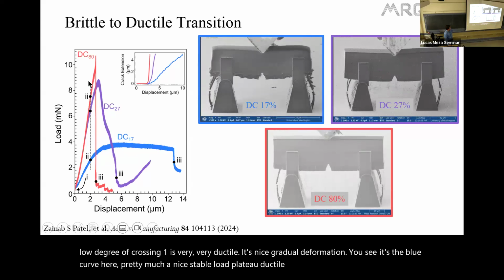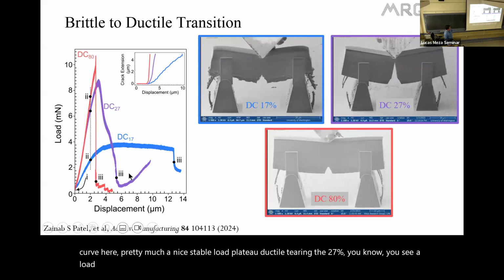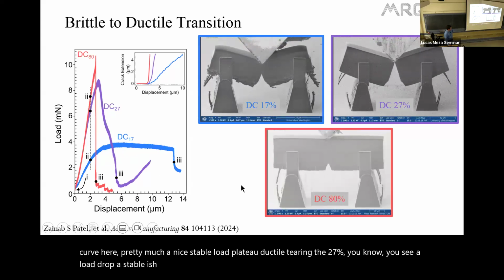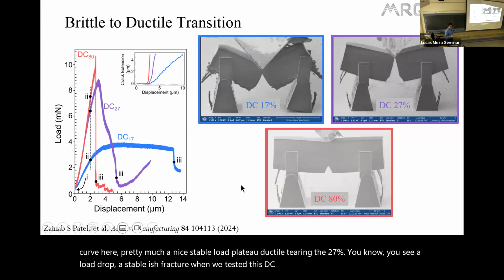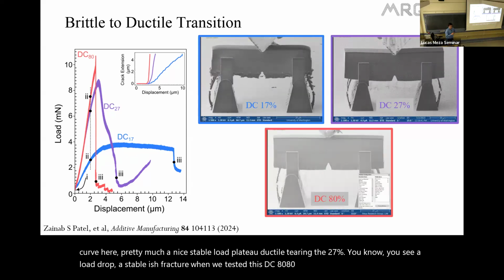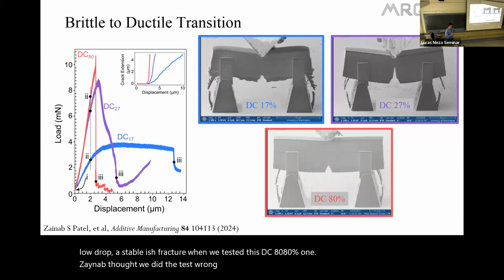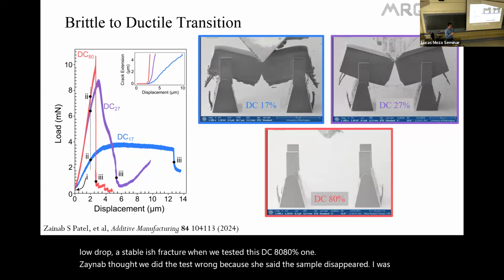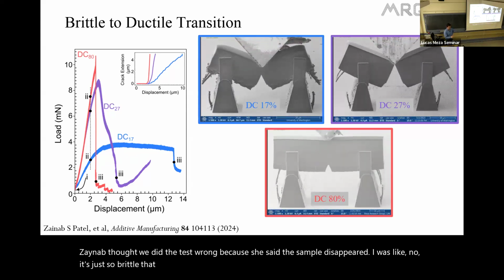The 27%, you see a load drop, a stable-ish fracture. When we tested this DC80, 80% one, Zainab thought we did the test wrong because she said the sample disappeared. I was like, no, it's just so brittle that it flew off the chip.